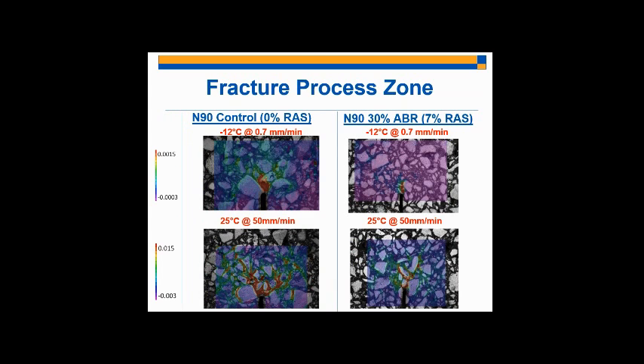And so what we've done is we've looked at the fracture process zone for different testing scenarios. We first started out with testing the same mixtures, our 0% RAS at minus 12 degrees Celsius, the classic SCB testing condition that I mentioned earlier, and at 25 degrees Celsius, 50 millimeters per minute. And you can see the difference in the fracture process zone. At minus 12 degrees Celsius, the lower temperature, the fracture process zone is limited to the crack tip region. It's not really extending much past the crack tip.